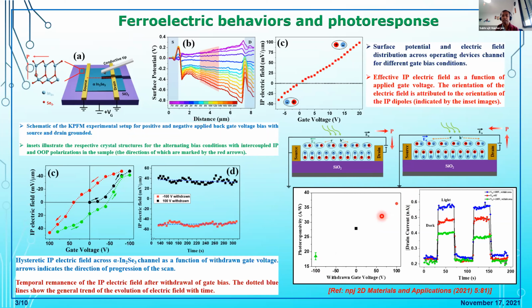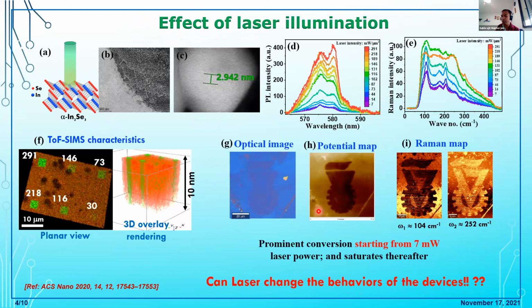But the range of this change is not very high. It is only from the 20 to 40 ampere per watt range. So we decided to go for the heterojunction devices because the heterojunctions might increase the enhancement factor. And we chose a post-fabrication process to change the device property to make the heterojunctions. So we decided to go with laser illumination, visible laser illumination, and check if the laser illumination can change the electrical as well as the optical property or not.